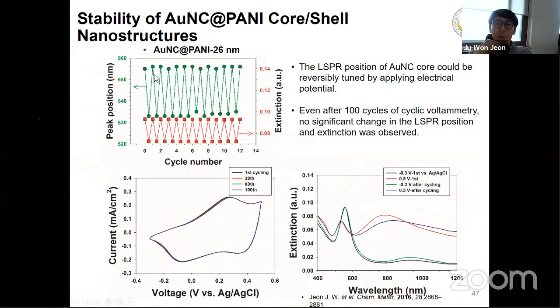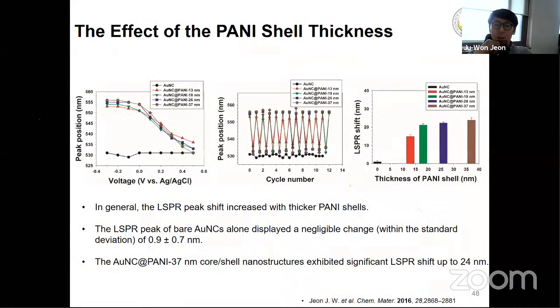And we can also modulate it continuously multiple times. So there is no kind of significant peak change when you apply high voltage and low voltage. So it can show very reversible behavior. And even after 100 cycles, it shows a very similar cyclic voltammogram, and the plasmonic peak position remained the same without any kind of shift.